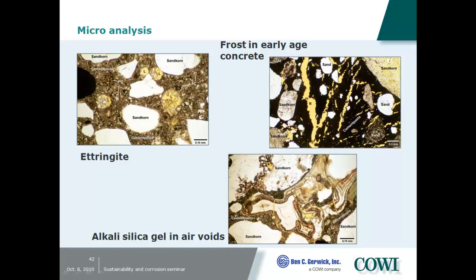This is a crack pattern. You can see it's only in the cement paste in this case. That's a sign of early age frost. You can also look at aggregate grains if alkali silica gel has formed. Very often you can follow a crack and then find the reacting aggregates a bit further down the crack.